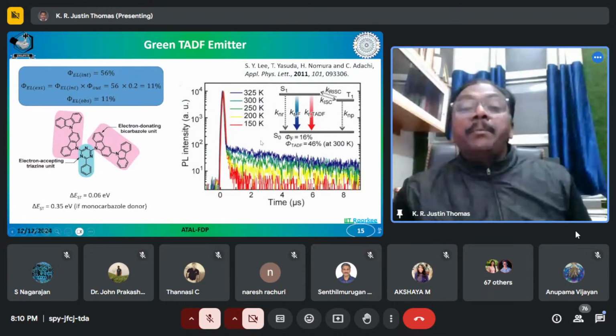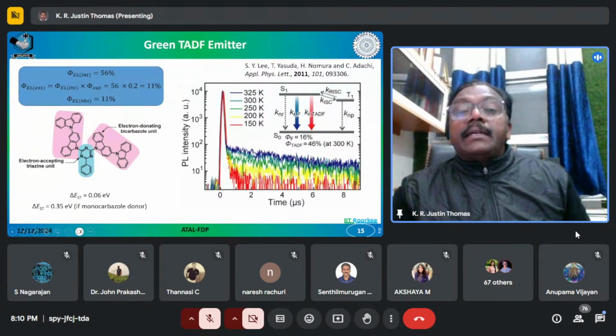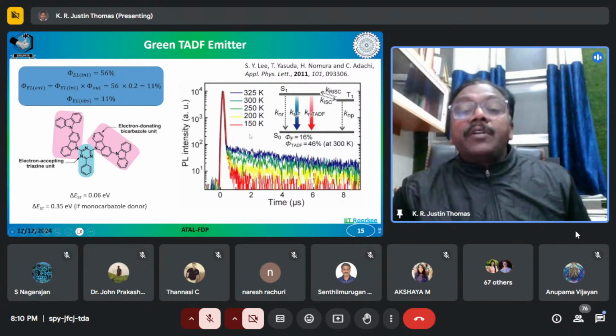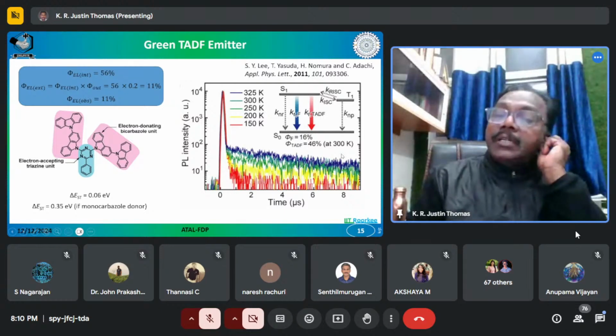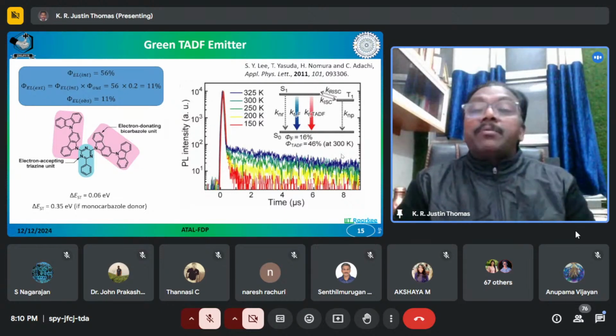Higher temperature improves the TADF characteristics of the molecule. You can see that the second delayed fluorescent component, which occurs at the longer lifetime, is seen at higher temperatures. So when you look at low temperature, that is 150 Kelvin, the red trace here, there is no delayed component. However, when you increase the temperature to room temperature and slightly beyond, you get the delayed fluorescence. So room temperature is good enough to facilitate the TADF in these kinds of molecules.